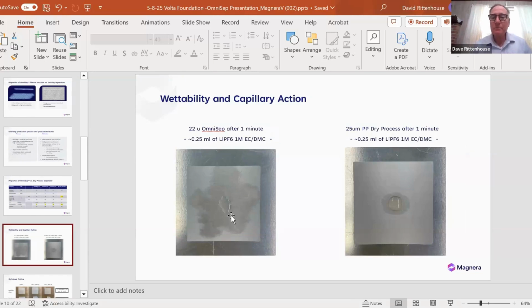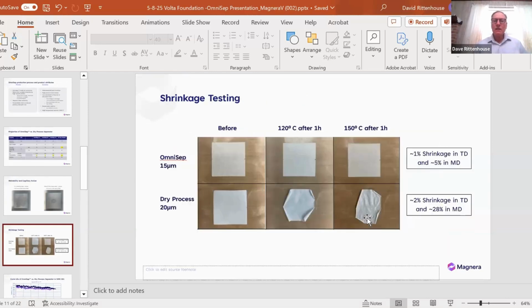So these pictures illustrate this point very well. This is the OmniSep 22 micron after 1 minute of a 0.25 ml drop of standard electrolyte. This is the 25 micron stretched film, and you can see that little droplet still remains.